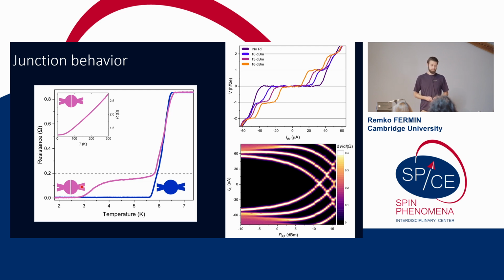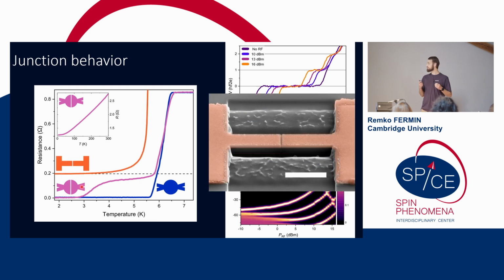All right. Then how do we know that the ferromagnetic vortex is responsible for generating the long-range triplets and not something else? In order to answer that question, we've made control samples shaped into a bar, and the natural magnetization of these bar devices at this scale is along the direction of the bar.